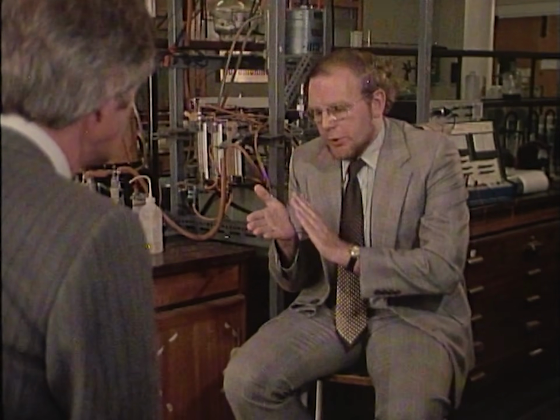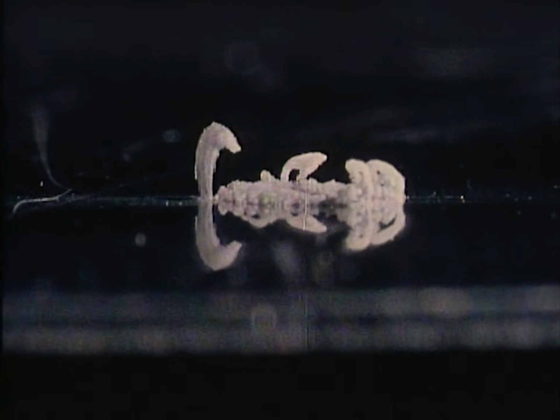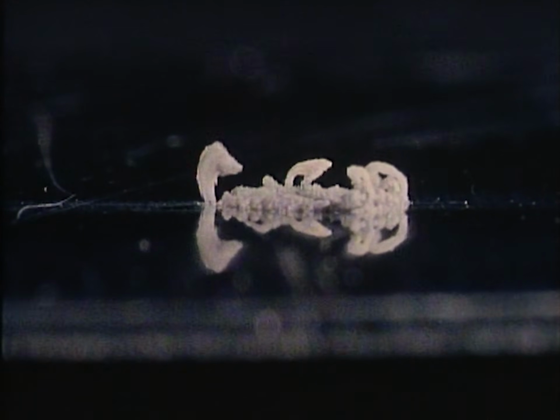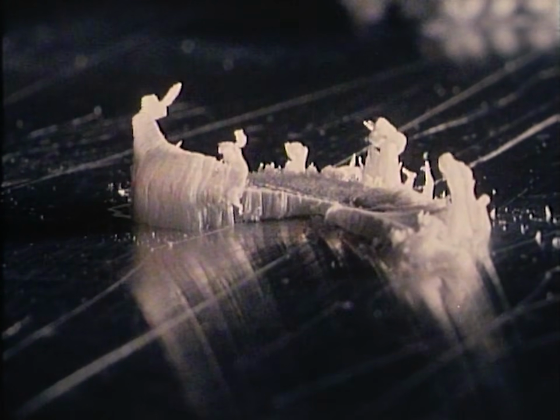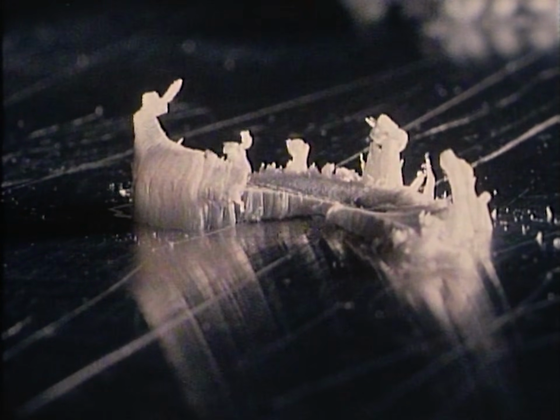On the other hand, if we alloy that with something above 13% chromium, which gives a stainless steel, we get a completely different corrosion product. We get, formed on the surface of the stainless steel, a very thin oxide layer. That thin oxide layer is what protects aluminium too, but this nice shiny piece has been painted with a chemical that stops the passive film forming, and it's corroding before your eyes.